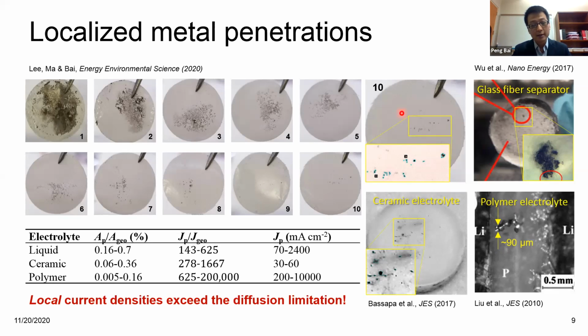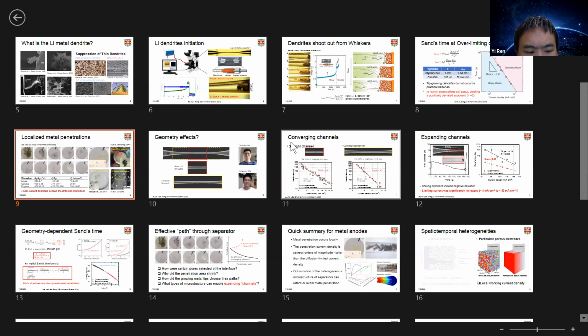And I think ideally we will have this kind of expanding conduction channel so that the penetration won't even happen, because when penetration tries to happen, it always expands. When you expand it, you lower your current density. So when you lower the current density, you will not be able to grow further. So that's why it's because of this kind of collective effective geometry. We think that, well, it's not exactly matching our capillary cell, but there is a geometric effect. Mm-hmm. I see. Yeah. Thank you.